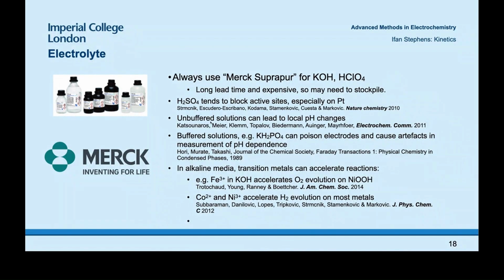Alternatively, you can use buffered solutions, but often the species used to buffer and hold the pH more stable, for example phosphate, can also poison electrodes in a similar way to sulfate anions. So they can cause a lot of artifacts in the measurement of actual pH dependence. What could be an apparent pH dependence would actually be due to anions from the electrolyte causing a change, blocking active sites. Similarly, people have also noted the cation has a strong effect in many reactions, including oxygen reduction or hydrogen evolution.